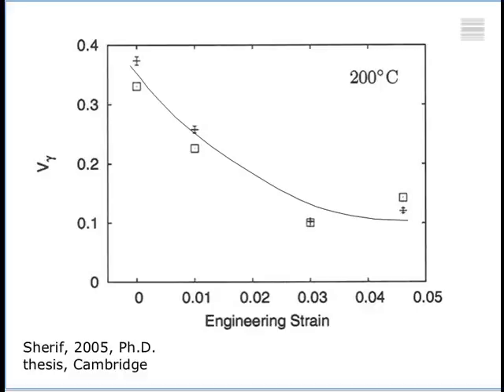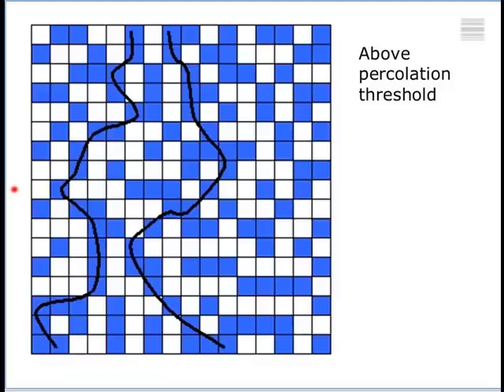So I'm going to explain a long story in a very simple way. So imagine that the blue color is the austenite and the white color is the ferrite. In this, I have sufficient blue material to continuously draw a line through the austenite. Okay? So we say that the fraction of austenite is greater than the percolation threshold. That means you can continually deform through the austenite.